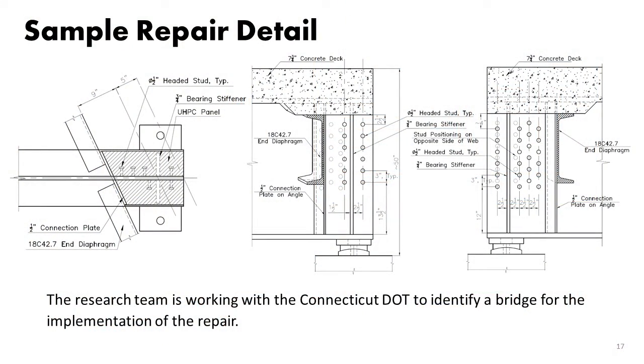And this shows what a standard detail looks like. It is a very complicated geometry. We intentionally picked it. It's a rail bridge detail from New Haven, highly skewed and complicated, and we wanted to see, in terms of feasibility, if we can accommodate that number of studs and how it's going to look. So we can see the studs that are welded. We cleared the corroded part based on what we got from inspection reports. And that shows the concrete cast. So essentially, you form a very strong concrete column at the end that takes care of transfer of bearing forces to the bearing.